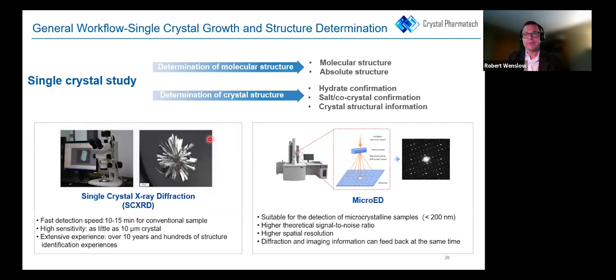So again, single crystal determination. We've got single crystal in-house, 10 to 15 milligrams of material, with someone that knows how to crystallize stuff. They work their magic, and you get a crystal structure. And if the crystals aren't big enough, then you go to micro ED. If you still can't get it through micro ED, is it absolutely necessary at this stage? No, but maybe for like 60 to 70% of your compounds, you could get this rapid crystal structure for structure identification, understanding how the bonds are going together. If it eventually goes to a filing, you're going to have this in the filing, etc.